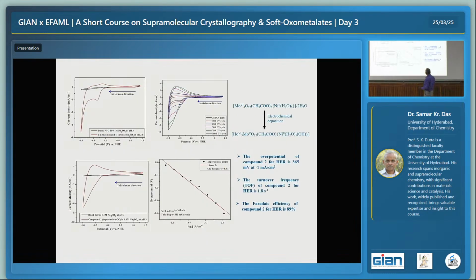What is that compound? That compound we characterized now. So this is the compound originally in aqueous solution. Now this is the deposited compound we characterized, and this is actually the catalyst that gives the hydrogen evolution. So what we believe is that molybdenum 6 goes to 5, but that remains the same even after the experiment. But nickel 2 goes to nickel 1 and nickel 1 reduces water and comes back to nickel 2 and makes the cycle. So I'd like to draw your attention that this compound is the deposited material, and it is also not anymore MoO3.